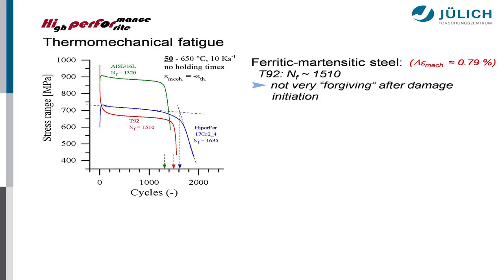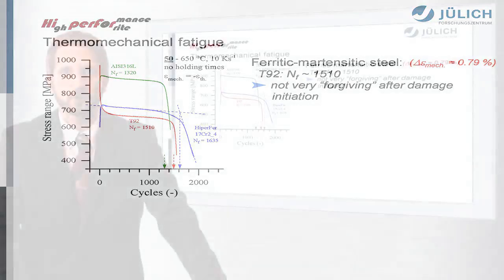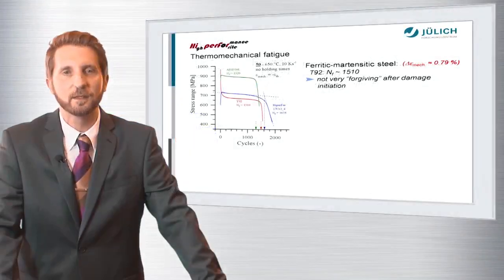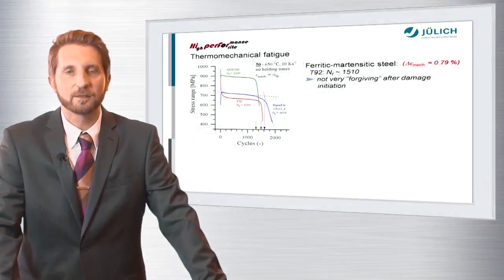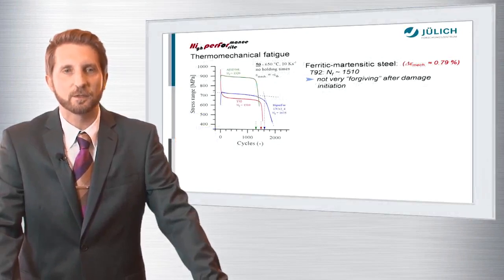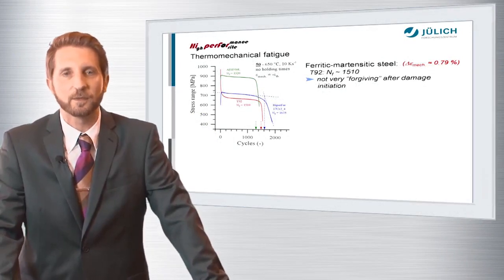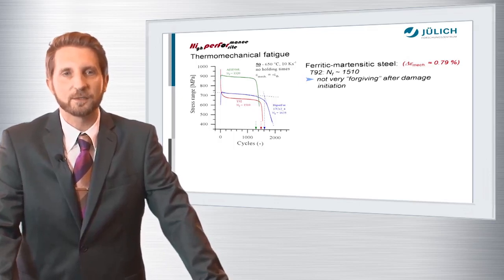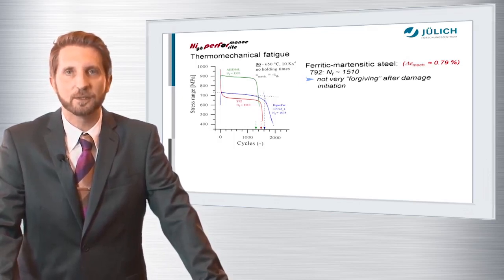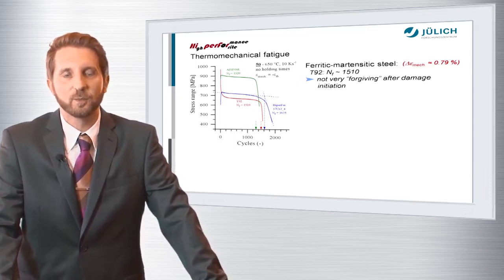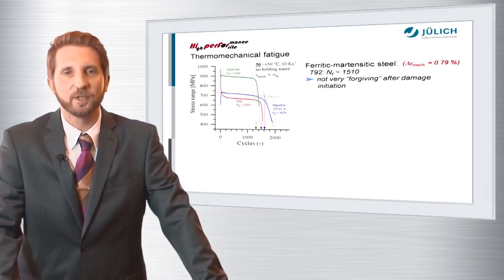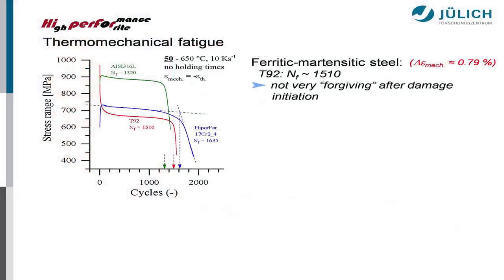And then you see the performance of 3 different material classes. Red is a ferritic martensitic grade, again T92, the most creep-resistant material that is available today. You see it reaches a very high stress range in the initial state. This is because of excess dislocation density from martensitic transformation. But this recovers quite rapidly during the first, let's say, 50 cycles before the material enters a stable phase, and after approximately 1500 cycles, damage and failure comes quite rapidly, so the material is comparatively unforgiving.